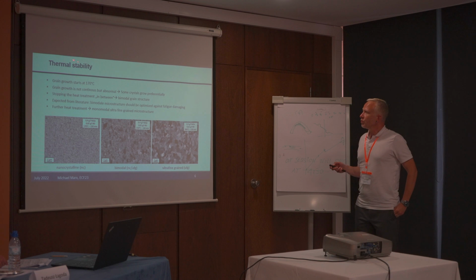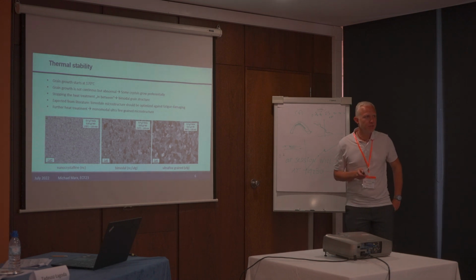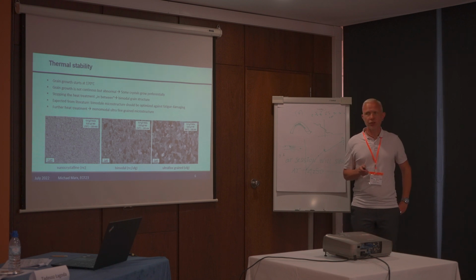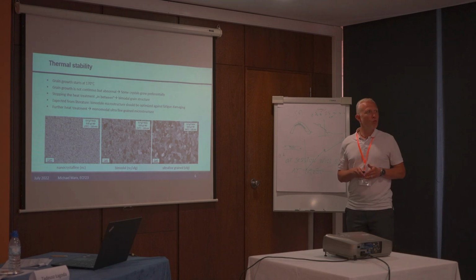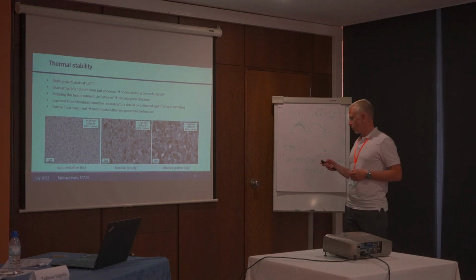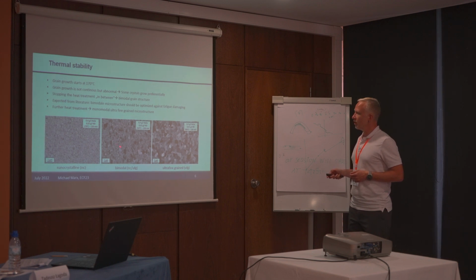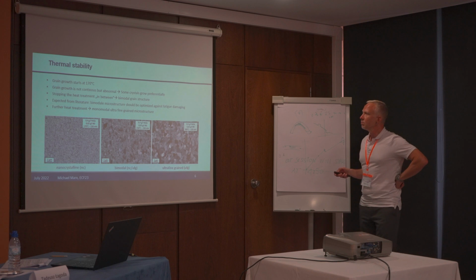So first we want to know about thermal stability. Grain growth starts at 170 degrees C, which is not very much. So if you have a small overheating maybe in your components, you may get grain growth and changing mechanical properties by this. The grain growth is not continuous, it's abnormal. Some crystals grow preferentially, as you may see here. You have a nanocrystalline microstructure and some ultrafine grains in between.